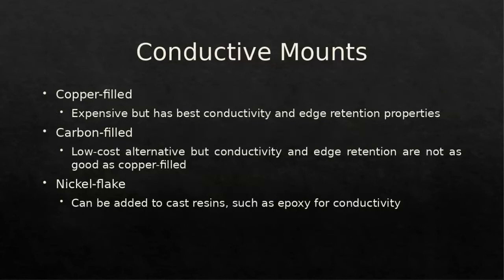Conductive mounts. This is very nice for anybody who is interested in doing SEM work with their mounted samples. I do encourage that you mount the sample using a conductive mount. You can use copper, carbon filled, and nickel flake. The copper filled is the most expensive, as anybody could probably guess, but it does have the best conductivity and edge retention properties. This is copper filled, so it is a metallic, and I believe they mix this with very fine silicon powders, which help with the edge retention to increase the hardness of the media that you're mounting your sample in. But for a lower cost alternative, you can always go with the carbon filled graphite. It has the conductivity, but the edge retention and the conductivity are not going to be as good as the copper filled, but it does get the job done.